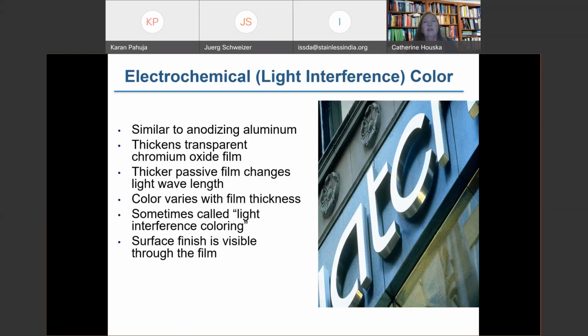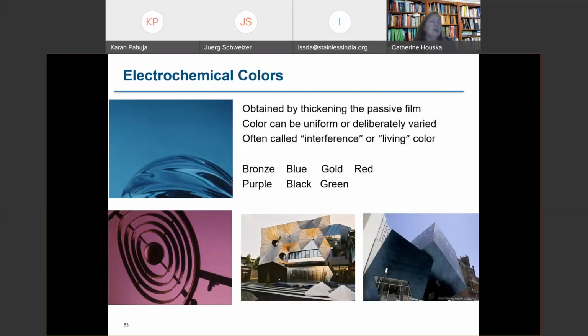And you can get very consistent color, and this is electrochemically colored stainless steel combined with embossing on the back of that sign. Here are two examples of very uniform color. You can get practically any color possible, but it's important to understand as you change the angle of viewing and as lighting conditions change, then the color will change.